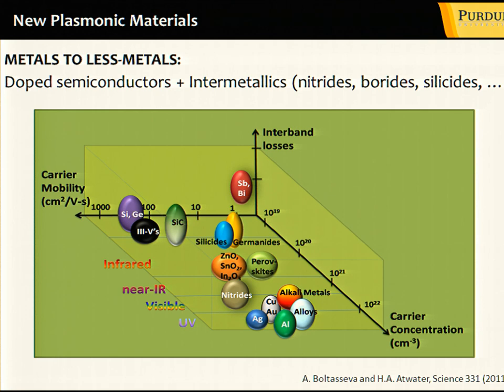And this is a very important work, in my opinion, done by Harry Atwater and Alexandra Boltasseva, where they actually showed a roadmap for developing new material components and showed that you could design and engineer these plasmonic properties by using very different approaches, making metals less metallic, and in that sense, materials such as intermetallics, for example, are very promising. Or using, for example, transparent conducting oxides, which you could dope to a very high level, making them plasmonic, for example, in the near infrared part of the spectrum.